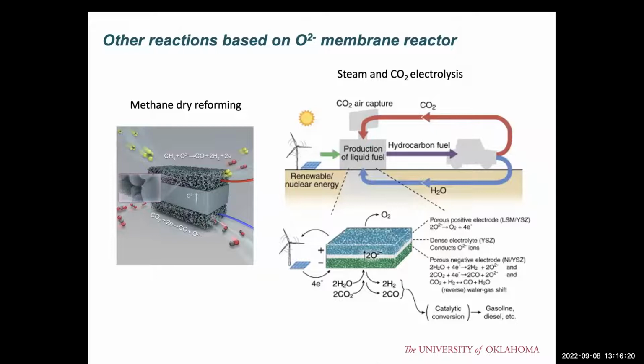And what else? For the hydrogen beyond, right? For the oxygen ion conducting, we can also use SOC for the methane dry reforming. As you can see here, if we have the methane feeding at one side and then CO2 at the other side, the methane can be converted into CO, carbon monoxide, and then oxygen transfers through the membrane to oxidize